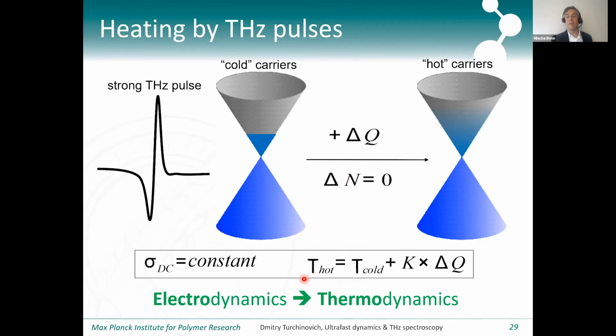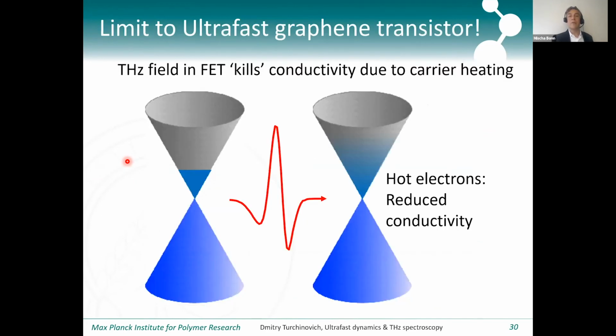And so what happens is that you can explain this seemingly intricate electrodynamics by simple thermodynamics, and it's really simply the temperature of the electrons that determines the response of the sample. The temperature increases during the terahertz pulse, and we can account for all of that. We find that we can reach temperatures of up to 1,000 or a few thousand Kelvin in these simple tabletop experiments. So there's a limit to ultrafast graphene transistors, which is really determined by an intrinsic property of the graphene. The terahertz field that you need to operate an FET actually kills the conductivity due to the heating of carriers. It's not that the whole device overheats, but simply that the electrons get very hot, and those hot electrons are not actually conductive anymore at those high frequencies.